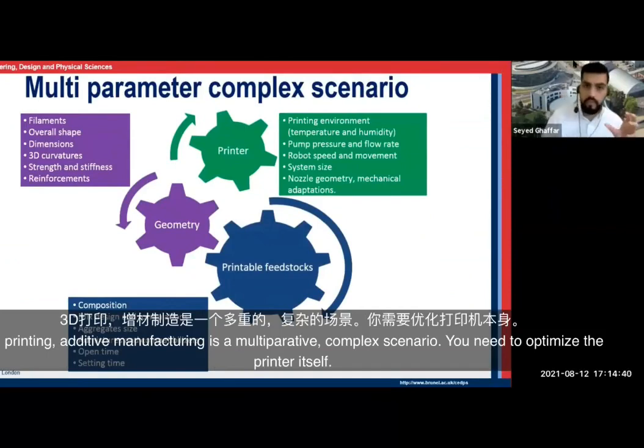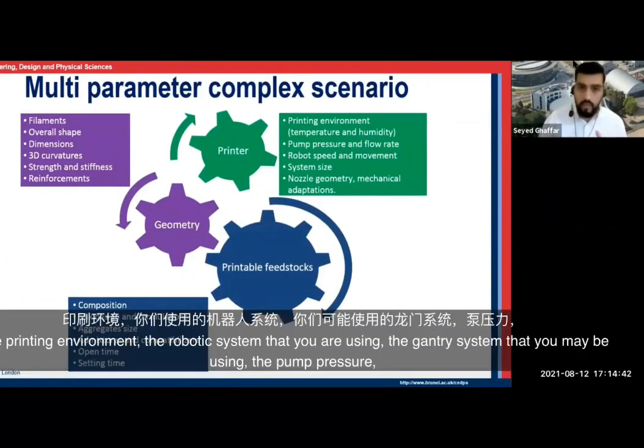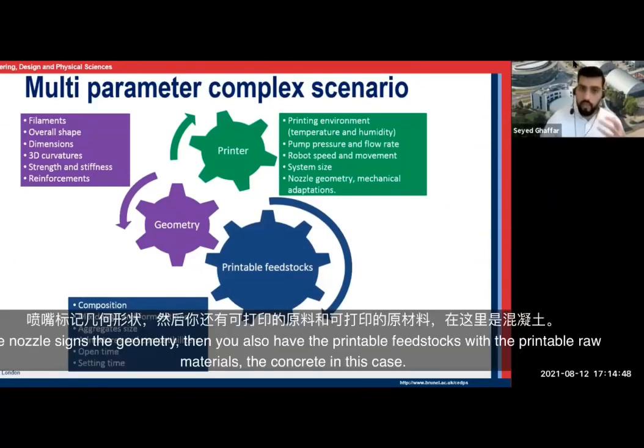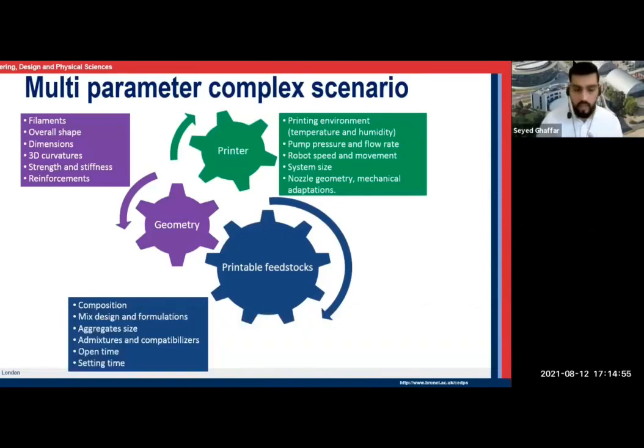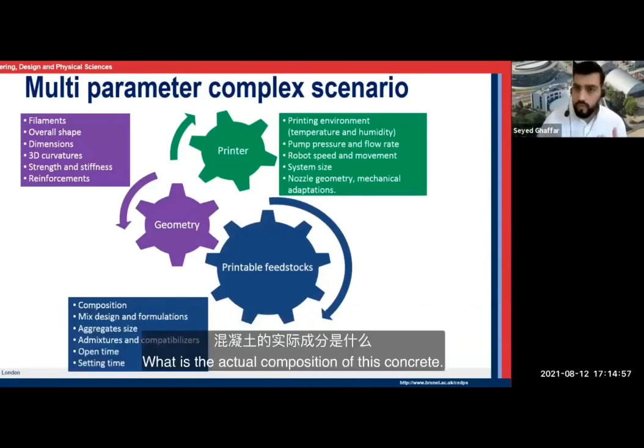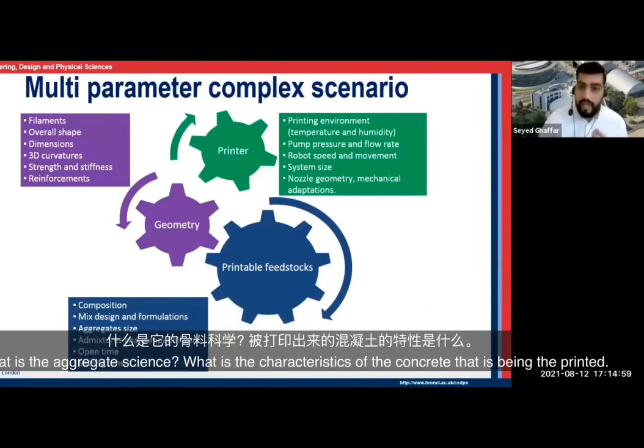You need to optimize the printer itself, the printing environment, the robotic system that you're using, the gantry system that you may be using, the pump pressure, the nozzle size, the geometry. Then you also have the printable feedstock, so the printable raw materials, the concrete in this case. What is the actual composition of this concrete? What is the aggregate size?